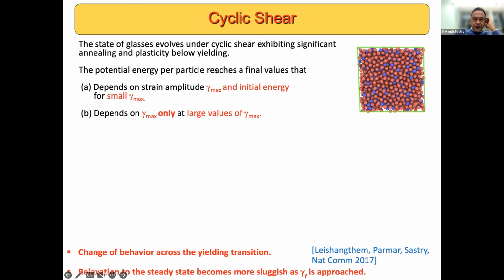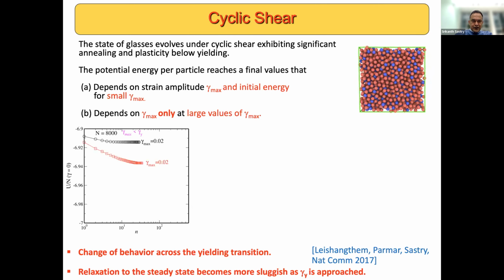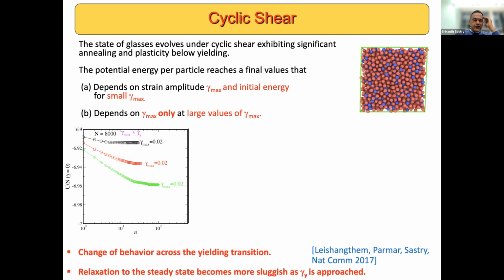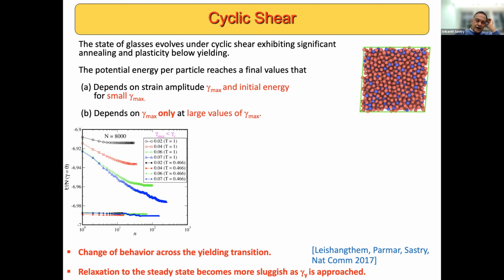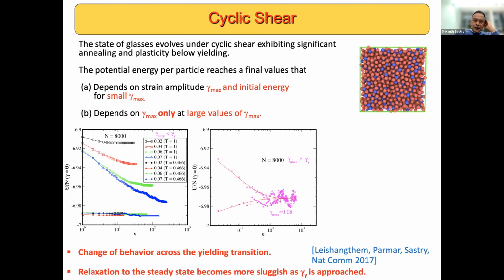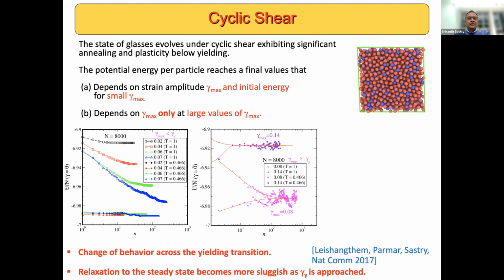If one looks at the potential energy per particle as one quantity to monitor, there are two regimes. As I mentioned, in the first regime, the final energy that I reach after a number of cycles depends on the strain amplitude, as I show here. So I'm getting to lower and lower energies with increasing strain amplitude, but it also depends on the initial state, and the final energies that I reach have memory of my initial state, so I don't go into any kind of an ergodic situation. On the other hand, if one is looking at sufficiently large strain amplitudes, then regardless of what initial state I start with, I end up going to the same final state. And this final state now has energies which increase with the amplitude of the strain that I apply.